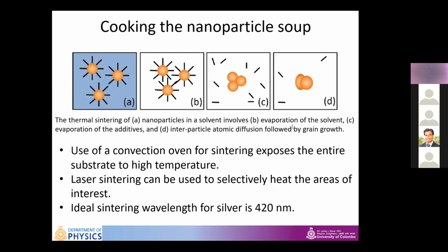Now we have the ink and we deposited it onto a piece of paper. Once we put down this ink or the soup, I told you that it's not conducting. So we need to cook the nanoparticle soup. In this multi-step procedure shown in the picture, A to B to C to D, that we try to make the ink conducting, we first have to evaporate all the solvent in the ink. So once we evaporate, we get rid of the blue color liquid solvent. Then we should further evaporate the organic additives. Those are those sticky things.